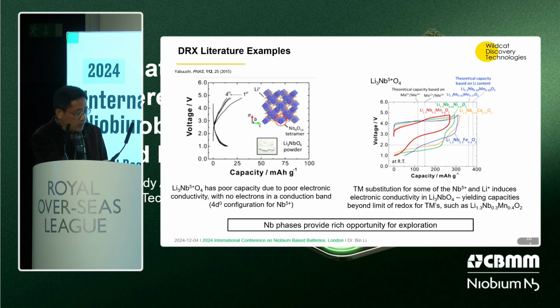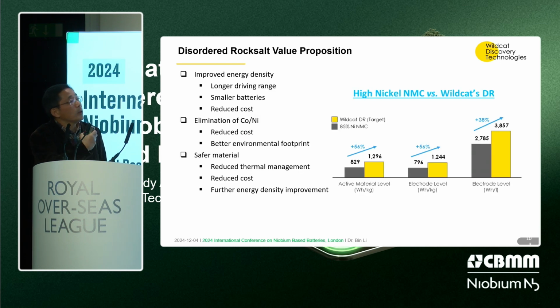But you can see this material started with a very high amount of niobium. But why do we want to work on this material? This material does show a higher energy density in terms of gravimetric, almost 50% higher than high nickel, 85% nickel. And the volumetric energy difference is a little smaller because of relatively low true density. These materials also show better safety, which I will show some data on later.